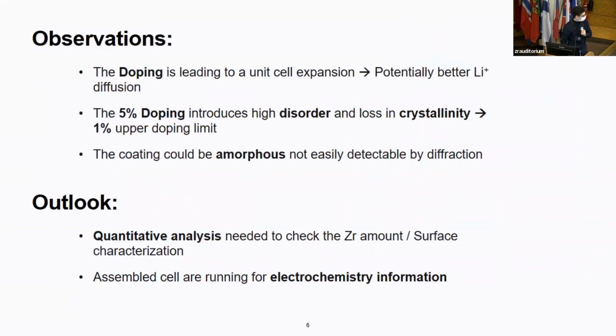We can make some observations with this data: the doping is leading to a unit cell expansion, is modifying the crystal, and potentially we can have better lithium diffusion, improving the performance of the system. But when the doping is too much, we are introducing disorder and we are also losing crystallinity, which means that we have to rescale the doping, and we cannot dope the material too much, which is quite obvious. The coating could be amorphous, so it's not easily detectable by diffraction.